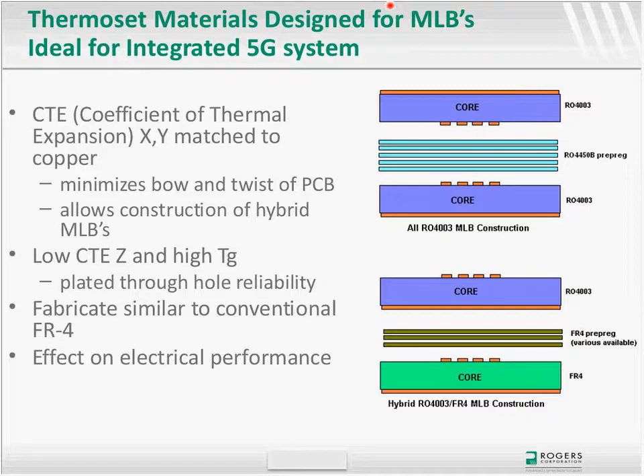A lot of times the coefficient of thermal expansion is a mechanical property that is very, very important to consider here in matching all these layers together, to manufacture something that is flat. Usually these will go through some process where you need to put devices on the surface. It's usually an automated system, and flatness of boards is a very, very important factor. So materials that have similar coefficient of thermal expansion in the X and the Y is important. As we said, it minimizes the bow and twist. It allows for the construction of materials that may be not only of the material that you've selected for the RF, but also very important to have materials that have a close match to that FR4 for the hybrid construction.